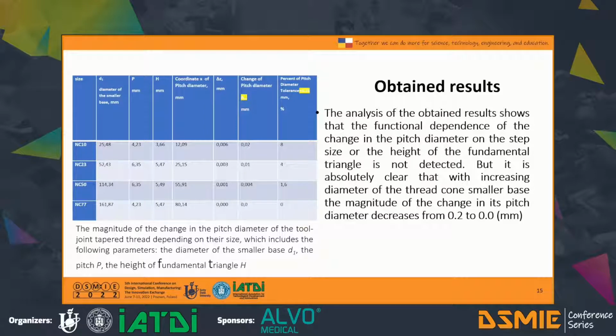Obtained results. The analysis of the obtained results shows that the functional dependence of the change in the pitch diameter on the step size or the height of the fundamental triangle is not detected, but it is absolutely clear that with increasing diameter of the thread cone smaller base, the magnitude of the change in its pitch diameter decreases from 0.2 to 0.0 mm.